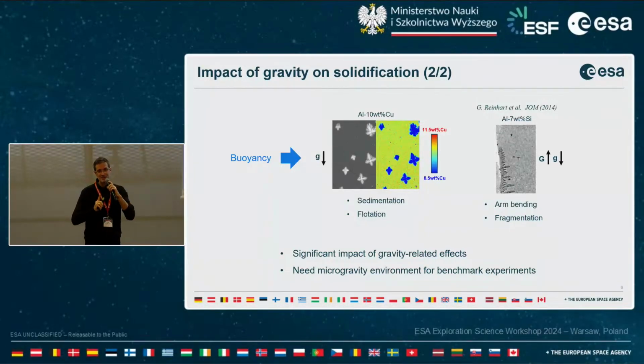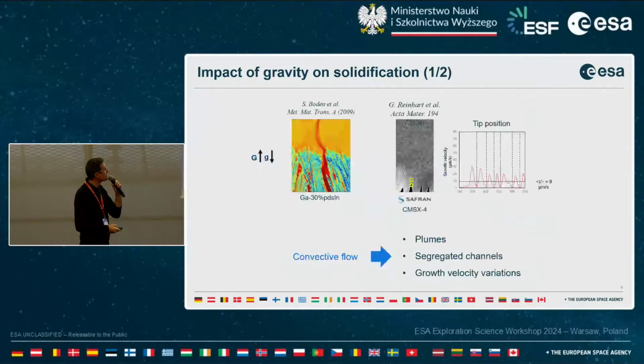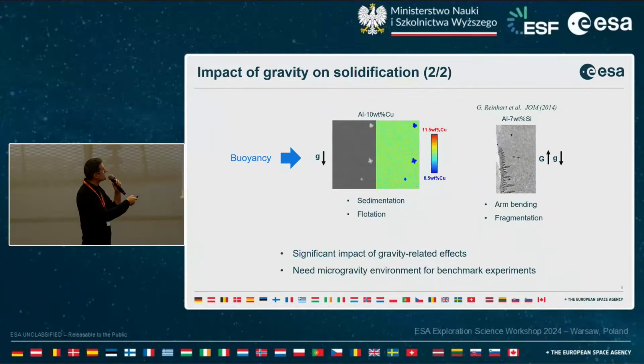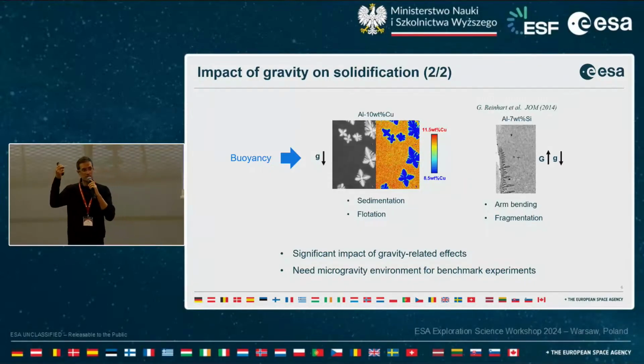But it is solidification, and so things are not that easy, because when you solidify, you reject solute. Here it is an aluminum copper alloy. Copper is heavy, so you reject heavy solute in the liquid, so the liquid will become denser and denser with time as long as you solidify. And what could happen? Well, after a while, the solid that was denser will become lighter, and the grains that were initially falling down will tend to float due to this density inversion and due to this enrichment in heavy solute of the liquid. So that's an effect of buoyancy.